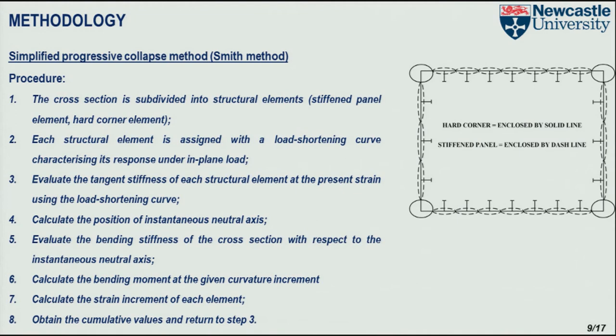And then since we now have the tangent stiffness of all the elements, we can evaluate the overall bending stiffness of the cross section with respect to the instantaneous neutral axis by using this relationship here. And now we have the bending stiffness of the cross section. So we know all these terms in the matrix. So for a given horizontal curvature and vertical bending curvature, we can solve this equation to calculate the bending moment increment. We do this calculation procedure incrementally, and finally we can get a bending moment curvature curve, and the peak of that curve is our ultimate ship hull strength.